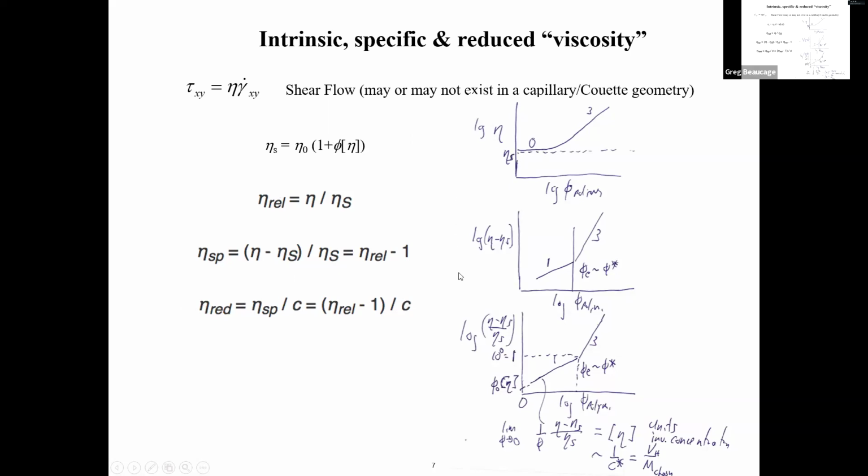So anyway, if you look at this in terms of plots, like say you just plotted the solution viscosity versus concentration, well, you'd get to the solvent viscosity. So you'd go down, and then all of a sudden it would go to solvent viscosity and it would just be constant because there's not much change with concentration at really low concentration. And the solvent's much larger than the change, so it just plateaus out there. So you have to subtract the solvent to get something reasonable. When you do that, you find out this depends on concentration. And then it depends higher once you get above the entanglement concentration.